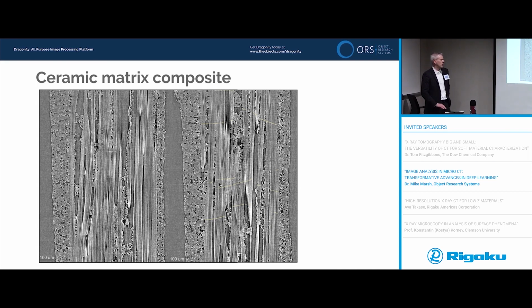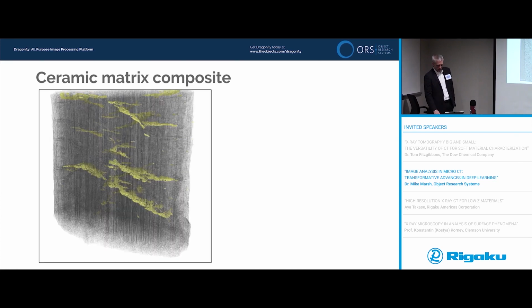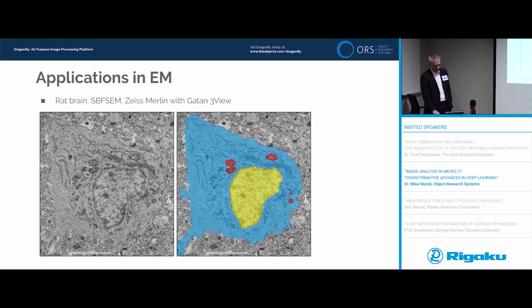And so Ali went through about 100 slices and just traced out cracks. This is not long, intensive painting. It's just tracing out a few cracks. So he did it in about an hour, and then trained a network, and then you can run the network, and now you can see what the cracks look like in 3D, so you can characterize the distance between the cracks, the angle the cracks make with the axis of the fiber bundle, etc.